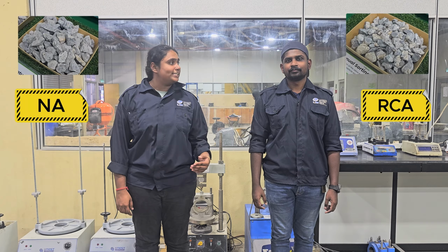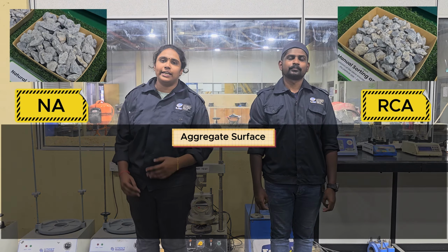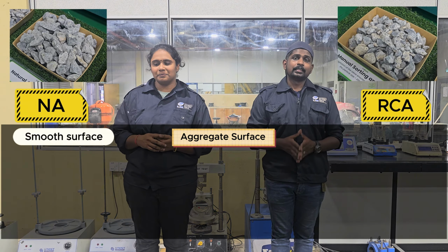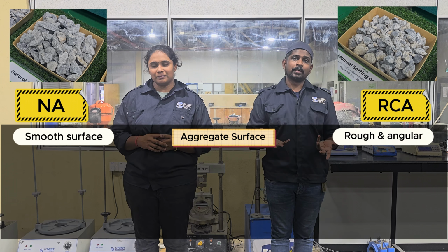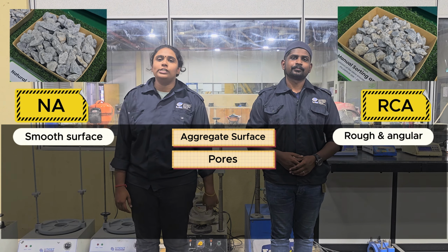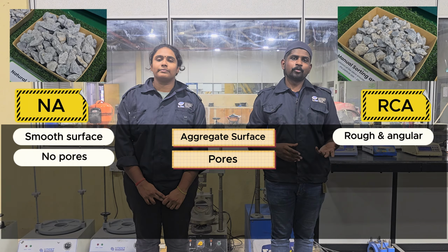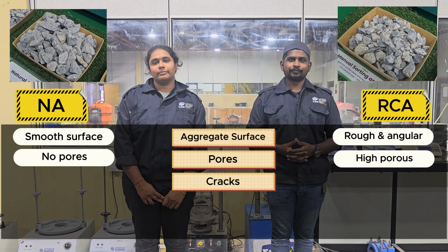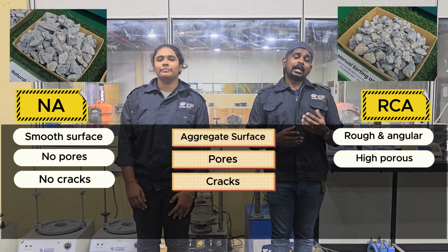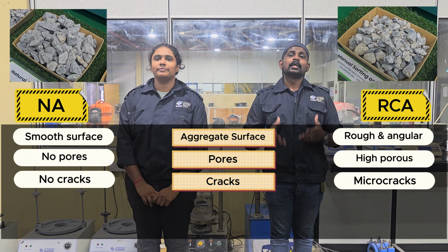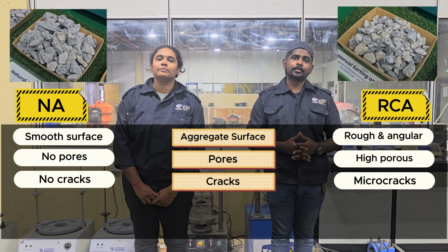Let's compare the aggregates. The surface of natural aggregate is smooth. The surface of RCA is rough and angular, caused by the crushing process. There are no pores in natural aggregate. RCA is highly porous, caused by the adhered mortar. There are no cracks in natural aggregates. RCA has many micro cracks caused by the crushing process and also the adhered mortar.